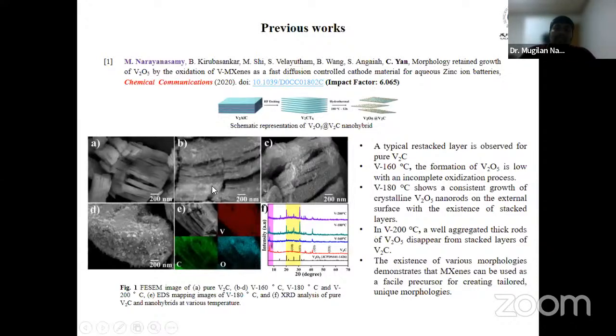At various degrees centigrade of hydrothermal heat treatment, I found that at 160 degrees centigrade, the formation of V2O5 is still incomplete. In V180 it is still consistent, and the growth of crystalline V2O5 on the external surface, with the existence of stacked layers, still persists, whereas in V200 the MXene was fully aggregated and V2C has fully disappeared from the stacked layers. The existence of various morphologies demonstrates this. MXenes can be used as a facile precursor for creating tailored unique morphologies.